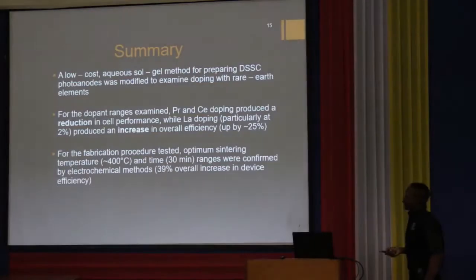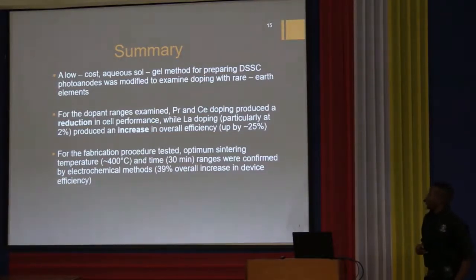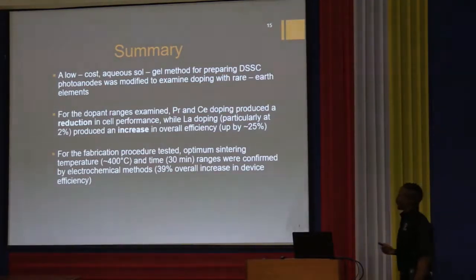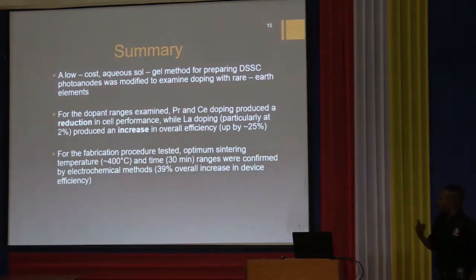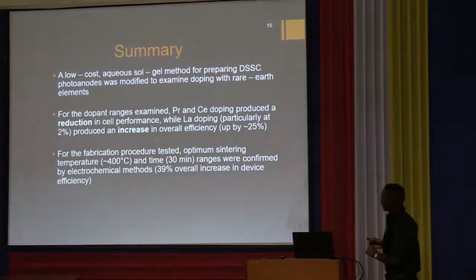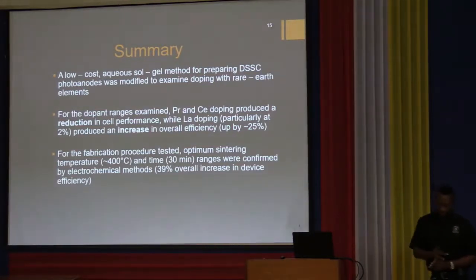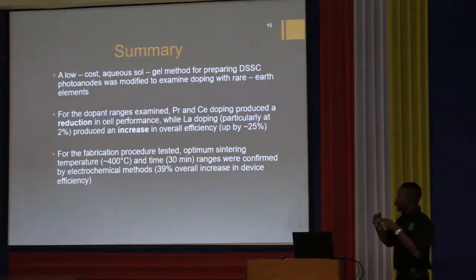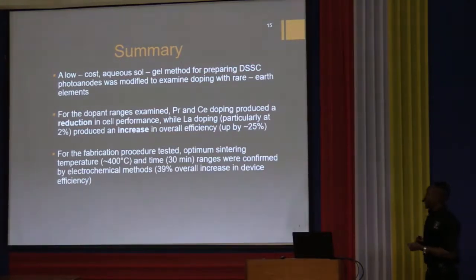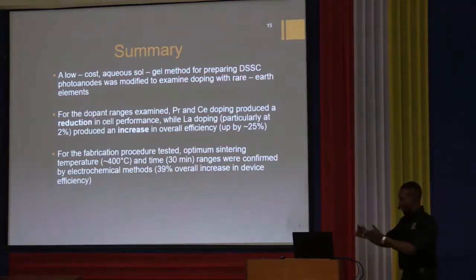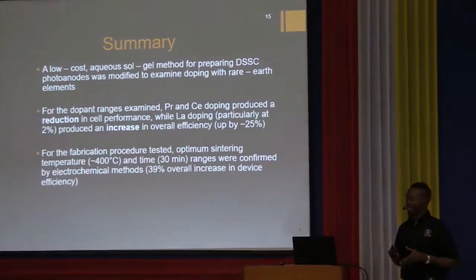All right? So in summary, we were able to use a low-cost aqueous method to prepare photoanodes for these cells. We investigated doping with rare earth elements to find the best dopant and best dopant level. And for the ranges that we examined, praseodymium and cerium produced a reduction in cell performance, while lanthanum doping at 2% in particular produced an increase in the overall efficiency. And that overall efficiency increase was by up to 25%. The optimum sintering temperature and time were 400 degrees Celsius and 30 minutes. And the overall increase in performance by optimization gave us a 39% increase in device efficiency.